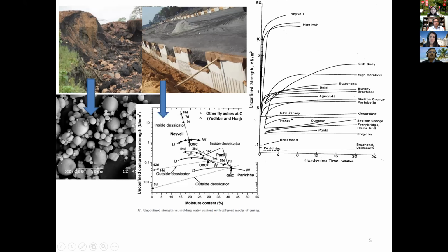Another problem started when the client came to us. They said that they were doing reinforced earth with fly ash, but as it dried off, it tilted. And if you see these properties, if I keep a compacted fly ash sample outside the desiccator, that means no moisture, the strength reduces considerably. For all three fly ashes, it is reduced considerably. That means it does not have cohesion. It is just called apparent cohesion. If water is there, then only it has some strength, otherwise not.